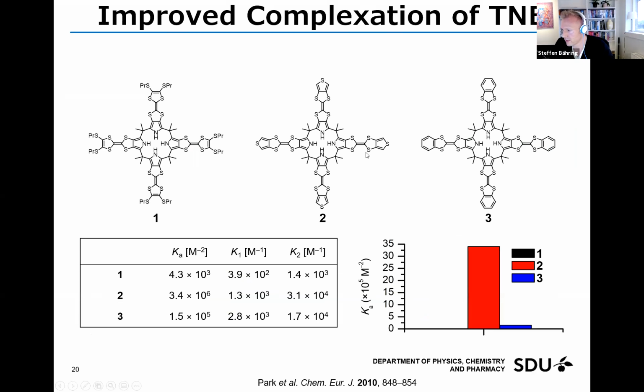Now going back to the pi-extended versions, the native thiopropyl compound 1 actually has the lowest oxidation potential compared to 2 and 3, meaning that it is actually a better electron donor. So one should, in essence, be better at interacting with the TNB molecule based on the CT interaction. But as you can see from the graphics, both 2 and 3 have higher binding constants, and 2 is binding much more strongly than 1, and 3 is also, as I tried to show on this schematic, where you can see that we can't really see the binding of 1 because it's so weak compared to the others. It's 10 to the 3rd, whereas 2 is 10 to the 6th.